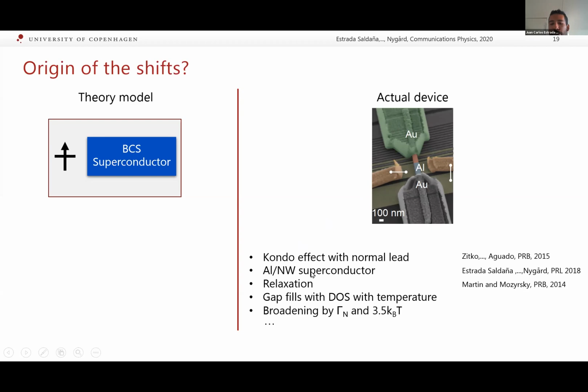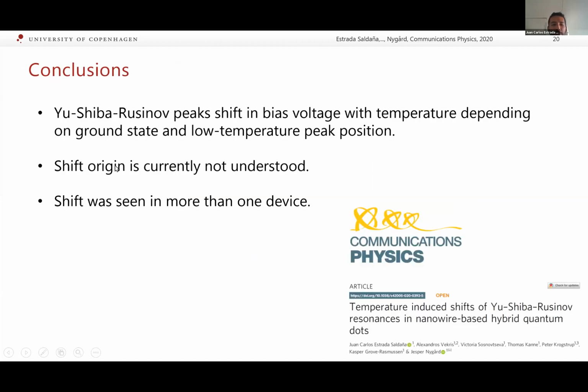We also have an aluminum nanowire superconducting lead. So the lead is not necessarily BCS, it's a hybrid. We have quasi-particle relaxation, even though I don't see how this could change the position of the peaks. And we have a gap that fills with density of states, and we have some broadening because of the normal lead. So with that, I reach my conclusions.